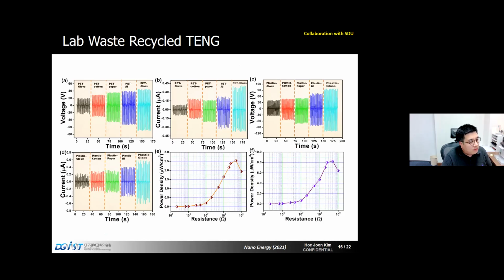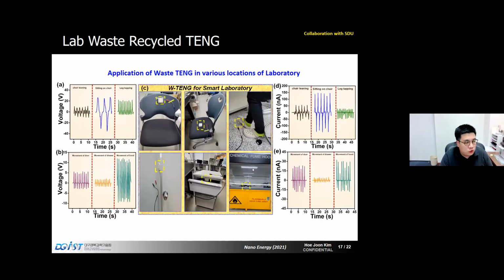So we have compared a lot of different materials such as glove, cotton, paper, aluminum, and glass. As you can see, depending on the materials combination, we were able to get different outputs. In this case, we were able to get a few microwatts per centimeter square. Again, this may not be sufficient, but they can be used for event detection, right?